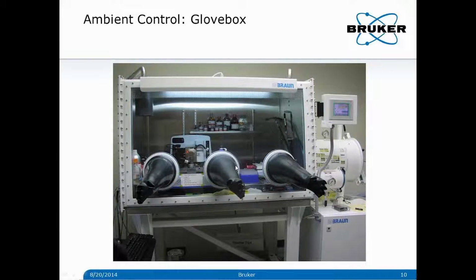So for this, we integrate our AFM with glovebox techniques. As you can see, the whole AFM is housed inside a glovebox. This glovebox is capable of providing atmospheric isolation, and this isolation is by a controlled, non-reactive environment. It is an argon-filled glovebox. It provides an environment with less than 1 ppm moisture and oxygen content.